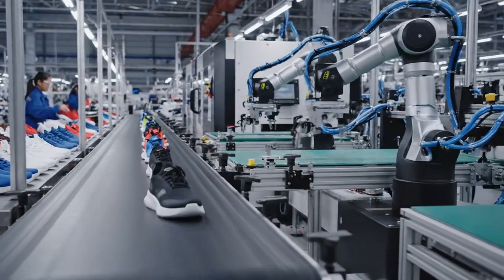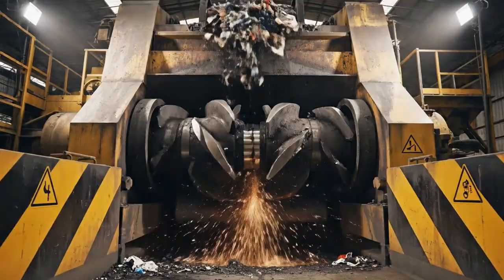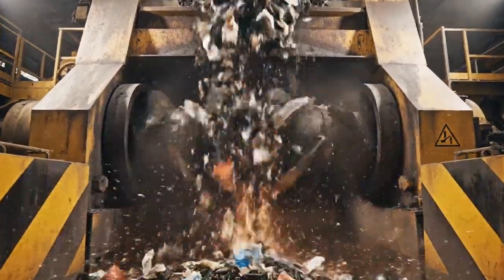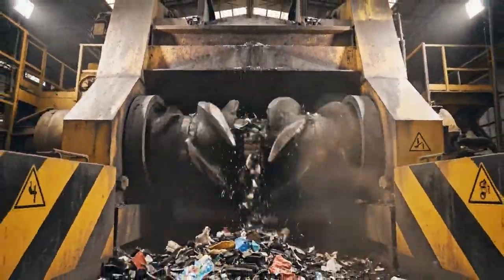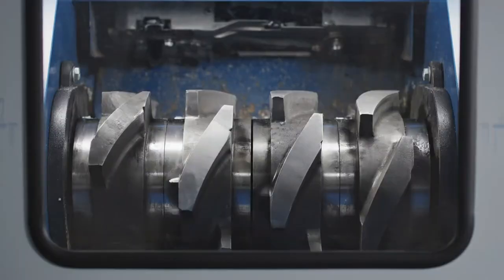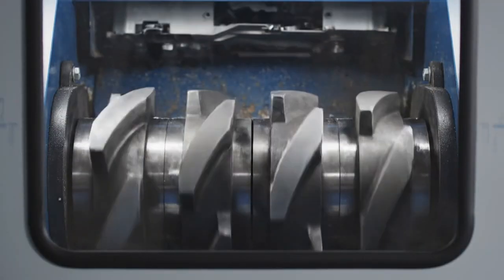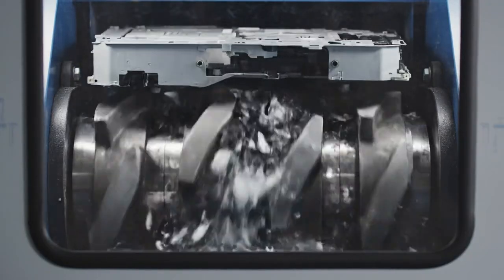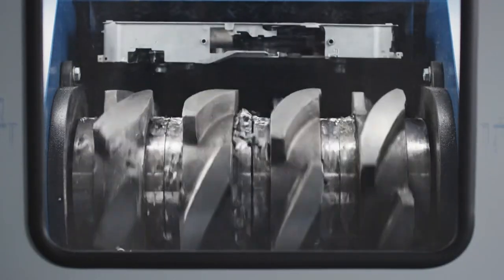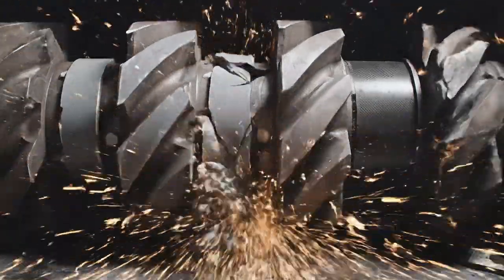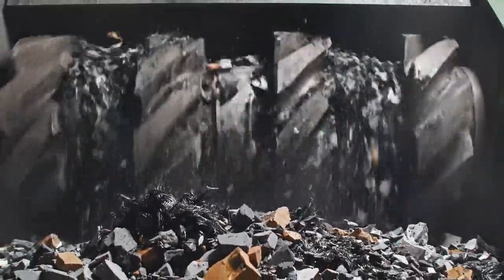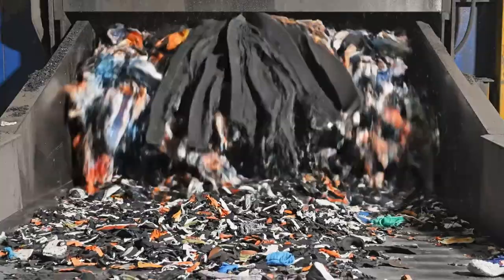shoe's chemical genealogy. From the sorting tables, the shoes advance to the first mechanized stage, the rough shredder, a horizontal shaft machine with dual rotors that counter-rotate at differential speeds. The geometry is precise, hardened steel teeth, each shaped like an industrial can opener blade, that intermesh with calculated clearances measured in millimeters. As shoes enter the shredding chamber, the rotors seize them with violent efficiency. The sound is apocalyptic, a grinding roar punctuated by sharp cracks as thermoplastic shanks fracture and carbon fiber plates shatter.